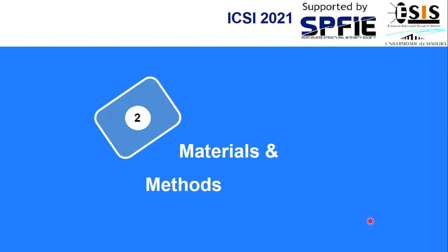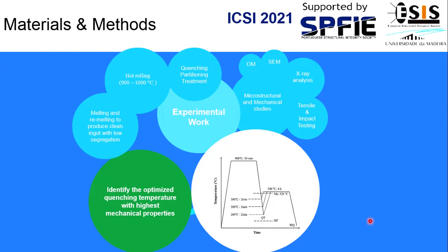Part 2, materials and methods. In this slide, you can see our methodology in producing an advanced high strength low carbon steel with considerable microstructural and mechanical properties. First of all, the scraps were melted and remelted to produce a cast ingot with low segregation. The remelting process was done by the electroslag remelting process, and in the second step, the produced ingots were rolled at 1000 degrees Celsius.